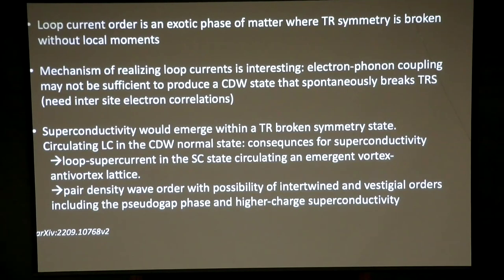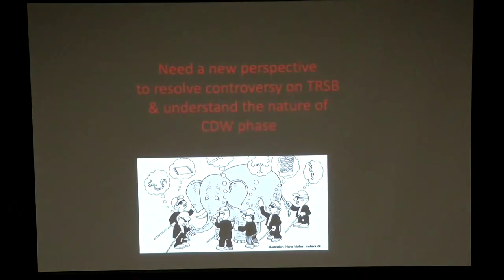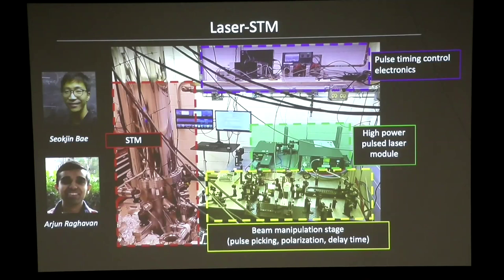And in fact, theory predicts that it does. Theory predicts that in the superconducting phase, you can have superconducting currents circling around, just like you had single electrons circling around. And if you have supercurrents circling around, you would get vortices and anti-vortices that occur in some kind of ordered pattern below the superconducting transition temperature. So indeed, this is a really interesting question. And so we need a new perspective to resolve this controversy. And that's where this laser STM comes in.